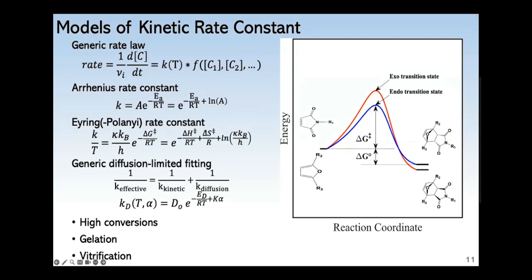Generic rate law is like the one that I have shown at the top, where you have a rate constant k, which just accounts for the temperature dependence of the reaction rate, multiplied by a function of the concentration of reactive species. And the most commonly used form of the rate constant to this day in most kinetic studies is the Arrhenius equation, which is described by a thermal activation barrier and a frequency factor A. But this should be emphasized as just an empirical model.